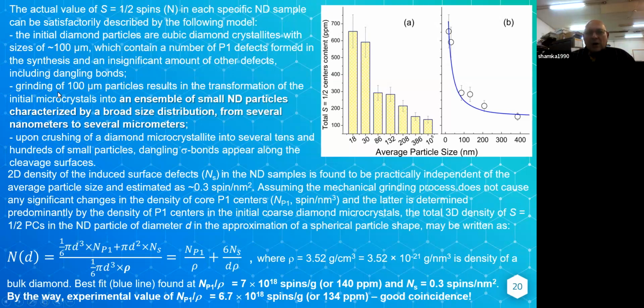When you start crushing these particles, it results in transformation of initial microcrystals into an ensemble of small nanodiamond particles, characterized by a broad size distribution from several nanometers to several micrometers. This is a reality. You cannot separate them by size perfectly. In any case, the distribution exists. Upon crushing of a diamond microparticle into several tens and hundreds of small particles, dangling sigma bonds appear along the cleavage surfaces.